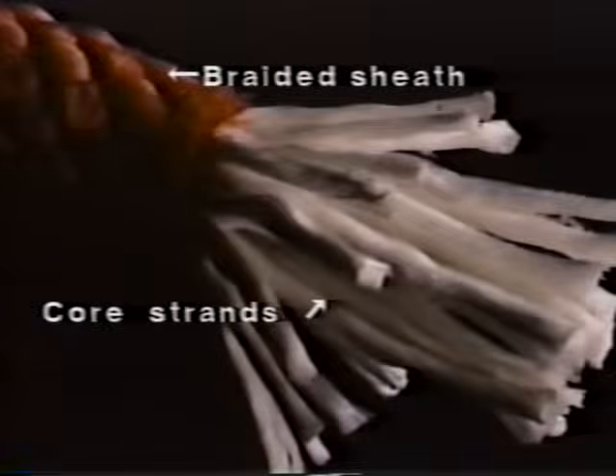The most common example of those would be large marine hawsers. Large marine lines tend to be braid-on-braid because it's a very elastic and very flexible type of construction. But the kern mantles themselves that we generally talk about in rescue have lower elasticity. They generally have fairly straight core bundles inside and a very tightly braided outer sheath. The strands in a stranded rope, because they're twisted, eventually all of the fibers come to the surface. Whereas in a kern mantle rope, the core or major load-bearing portion of the rope is never exposed at the surface. It is always protected by this outer jacket. And that outer jacket provides protection from abrasion and protection from dirt particles.